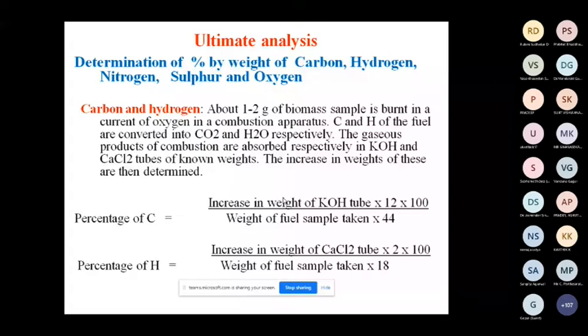So percentage of carbon is equal to increase in weight of KOH tube into 12 into 100 divided by weight of the sample and 44. The 44 is for CO2. If you have 44 of CO2, then 12 is carbon. So 12 over 44, the increase in weight, from this we can get the total CO2, and from total CO2, how much carbon. So divided by weight of the sample into 100, it will give you the percentage of carbon.